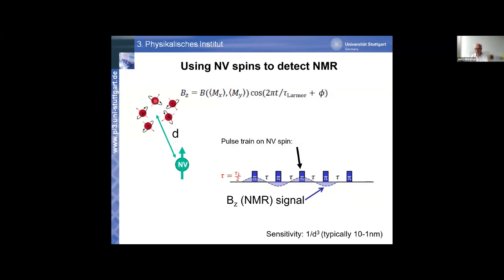The way we do this is, rather than just measuring the Larmor precession with a broadband magnetometer, we invert the electron spin of the magnetometer periodically. So we apply a pi pulse, or a NOT gate, every now and then with a spacing of tau to the electron sensor spin. And we do this exactly in registry, so commensurate with the oscillation of the magnetic field of the nuclear spin.